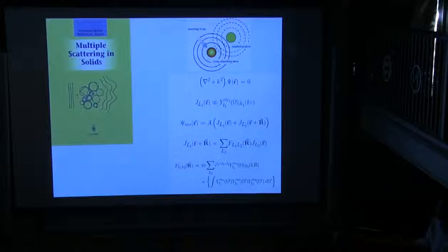When electrons propagate away from any given atomic center in a solid, because of the screening of other atoms, there is no Coulomb potential. They satisfy the wave equation asymptotically. Therefore, they're Bessel functions along with a spherical harmonic. If we try to build up a wave function that considers the multiple centers, this is a combination of atomic orbitals, if you like.